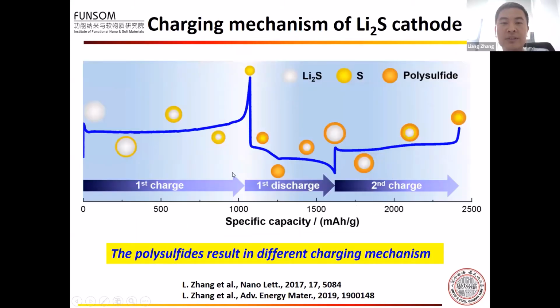So based on all the results above, we can get a clear picture of the charge mechanism of lithium sulfide. For the first charge process, the lithium sulfide is directly converted to elemental sulfur without the formation of lithium polysulfide. In the first discharge process, the elemental sulfur is first converted to lithium polysulfide and then to lithium sulfide. At the end of the first discharge process, not all the lithium polysulfide is converted to lithium sulfide, and therefore in the second charge process, the lithium sulfide is first converted to lithium polysulfide and then to elemental sulfur. So the most important conclusion of this research is that the polysulfide can result in a different charge mechanism for the first and the following charge processes.